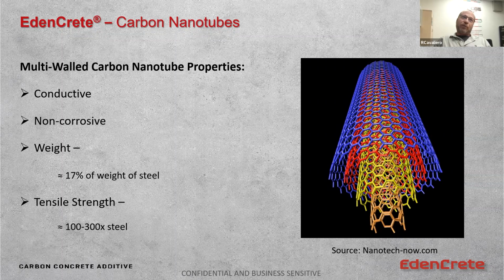The properties of carbon nanotubes that make them appealing, they're conductive. Along all of the surface areas here, especially for you electrical engineers, you might find this more interesting. These carbon nanotubes are extremely conductive along the surfaces of all of the walls. Now, when we use them in concrete, we're not using the conductive aspect. We're using them for a multitude of reasons, but one is to make the concrete structure, the hardened cement paste matrix, more robust, more able to endure, right? More durable. And so the carbon nanotubes, when we think about comparing them to what we currently use to reinforce concrete, right? Steel reinforcement, steel rebar. It's 60 KSI or 60,000 PSI yield strength.